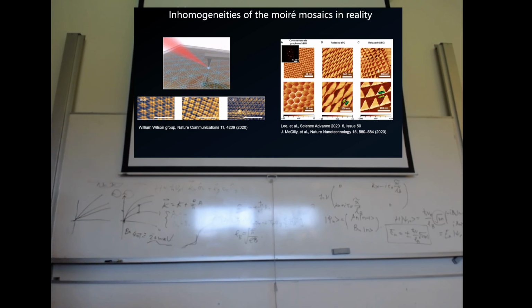I don't remember. You can see that locally, if you look at one triangle, it is well defined and quite okay. But at large scale, we have boundaries and twistings. These kinds of inhomogeneities are killing the global effect. If you make the samples, you have only like 1 in 20 devices working if you want to have this flat band. That's why it's very difficult.